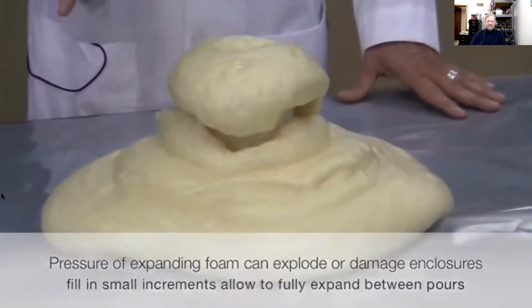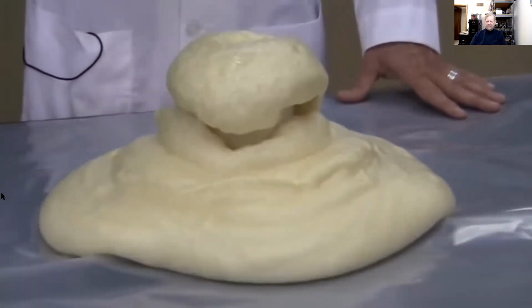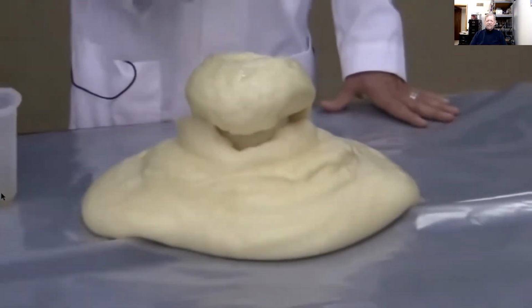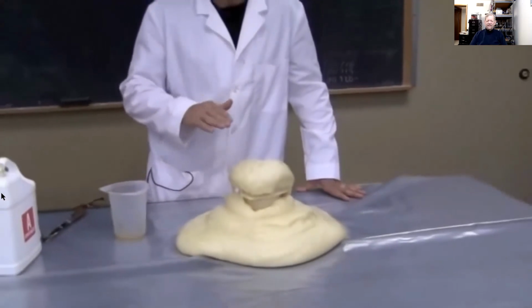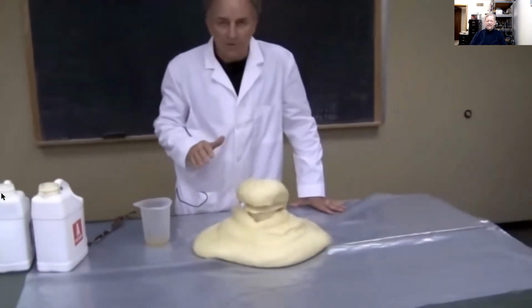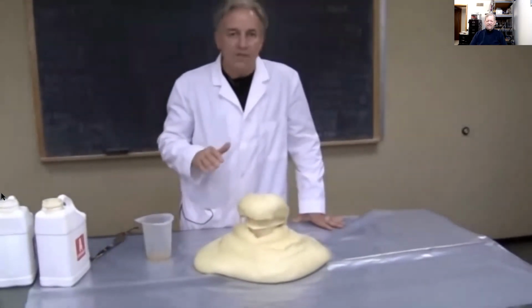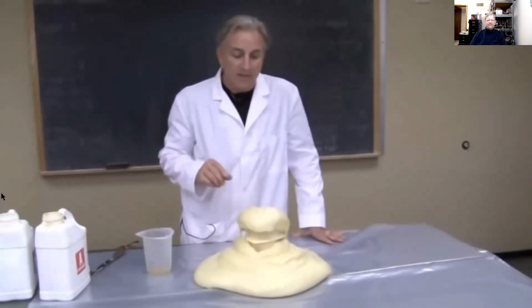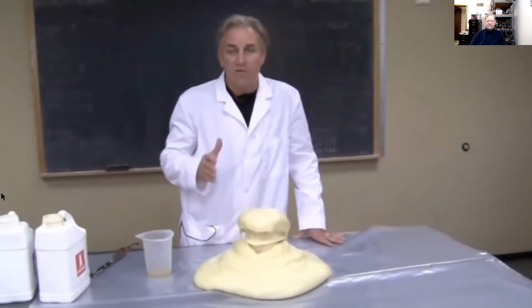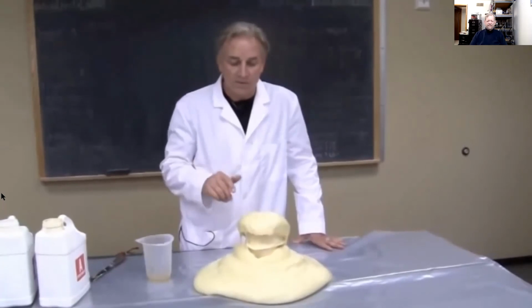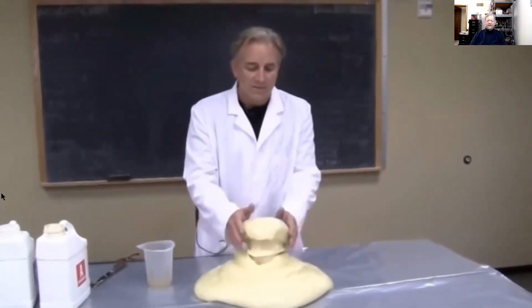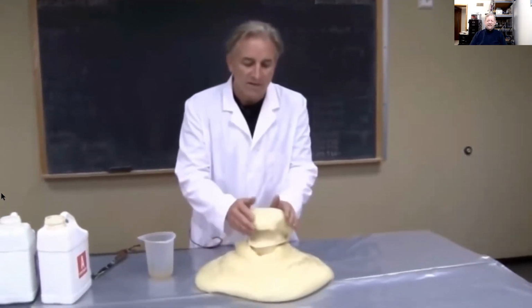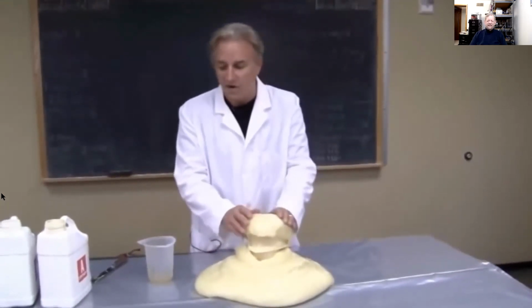Now, foam is sold in different densities, from very lightweight packaging foam, which is about 3/4 of a pound per cubic foot density, all the way up to heavy furniture foams, which can be as high as 15 to 20 pounds per cubic foot. Every time they go up in density, the carvability and the machinability goes up as well. You can see this is already forming a nice solid, and within a few more minutes I'll be able to pick this up and carve it for you.